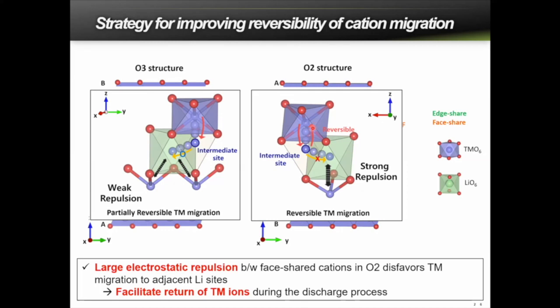On the other hand, in the O2 structure, this transition metal can go to the intermediate site, but when it hops to the nearest octahedral site, this octahedral site is strongly repulsed by the transition metal underneath. The reason there is a transition metal underneath this octahedral site is the different oxygen stacking, which allows the occupation of transition metal right here. So this strong repulsion should prohibit the migration, and the transition metal should migrate back to its intermediate tetrahedral site, so it's locked here.